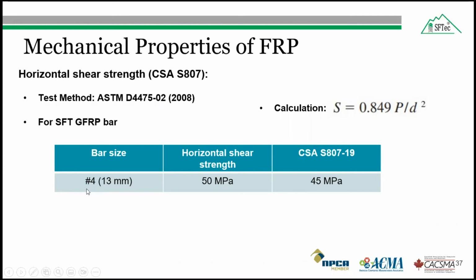And for the SFTec glass fiber reinforced polymer number 4 bar, the average horizontal shear strength was 50 megapascal, which was greater than the CSA S807. So this test is only required by the Canadian code CSA S807.